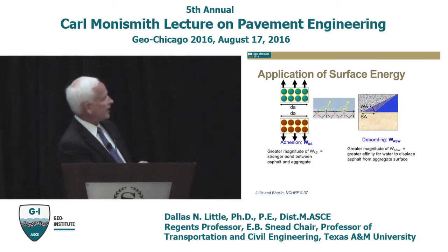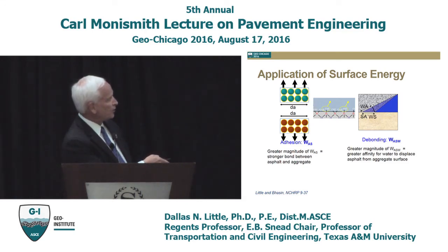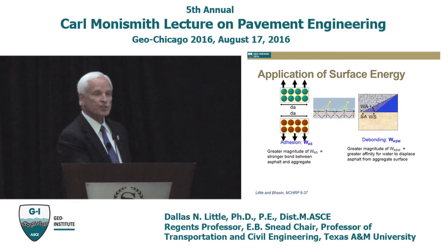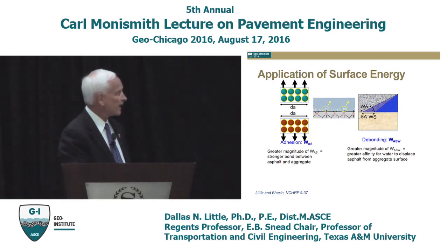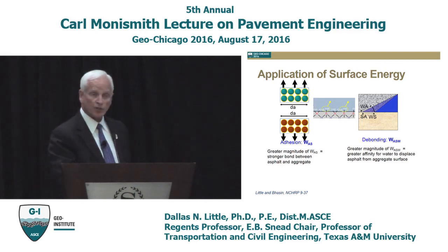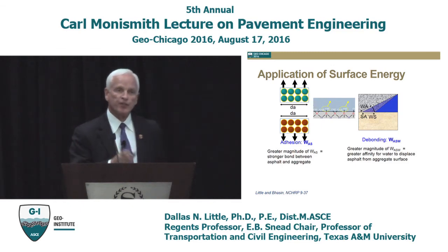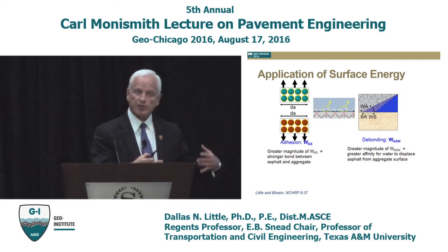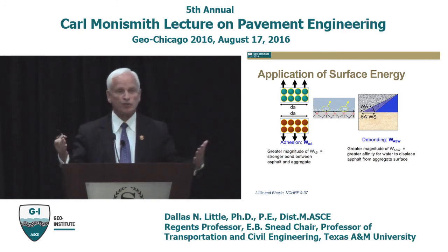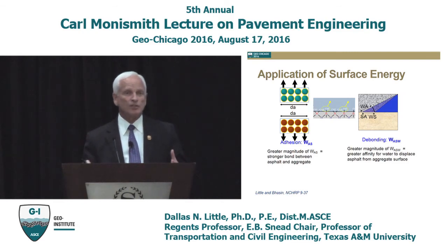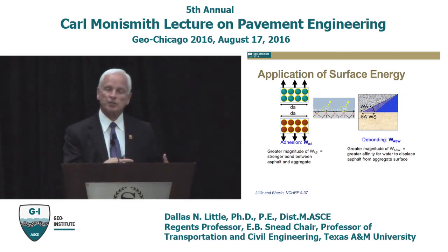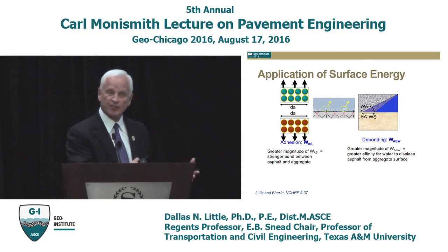Now over on the right-hand side is a little animation of what happens when water gets in the way. When water gets in the way, which is the blue stuff, we'll say that the gray is the asphalt and this is the stone, the water replaces that asphalt-stone interface. And when that happens, what you'll find is Gibbs free energy becomes negative. Gibbs free energy becomes negative virtually all the time. What that means, when Gibbs free energy becomes negative, is that the process is spontaneous. So that means that water almost always wants to replace asphalt if it gets there. That's bad news.